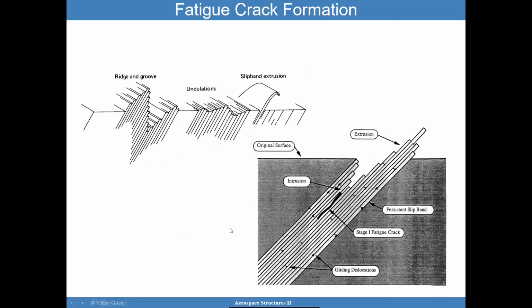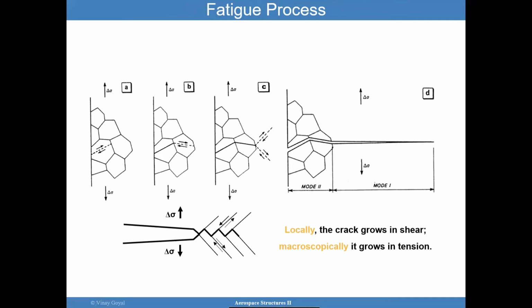Here you have a little more detail about the initiation process. That's your original surface. You have some amount of intrusion, some amount of extrusion, and then you have the persistent slip bands. We have this stage 1 fatigue crack growth, and you have all these gliding dislocations. But as this occurs and it propagates further, then it will become mode 1. So it starts sliding and then turns into mode 1. And here you have another view of what we're talking about. In this case, you have the loading direction. Again, sliding, and then you're going to have opening. So again, mode 2 and then mode 1. Locally, the crack grows in shear, macroscopically it grows in tension. And then here's an example of what could be happening to the crack tip, as you see.